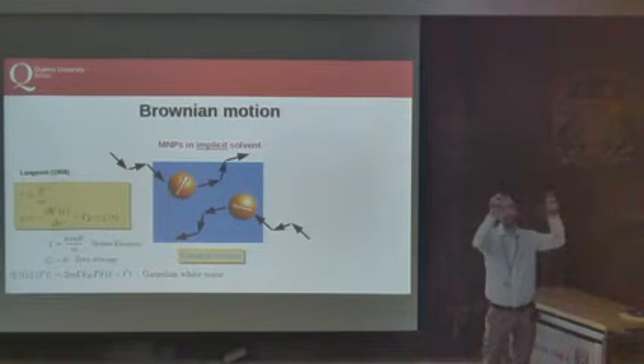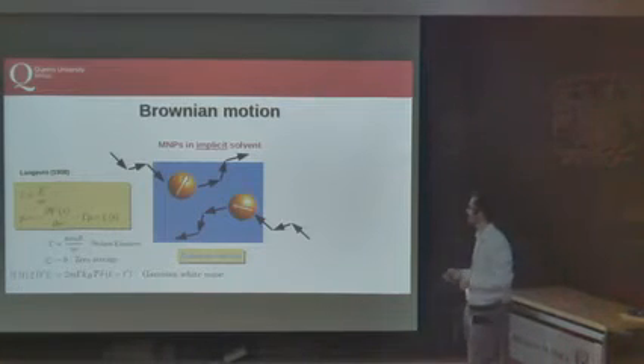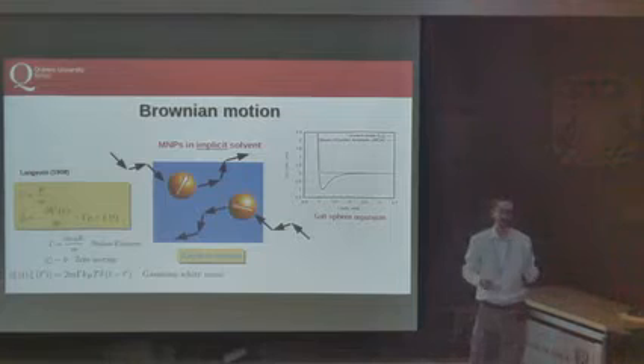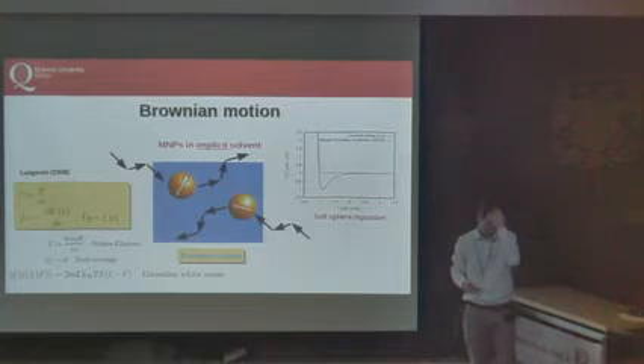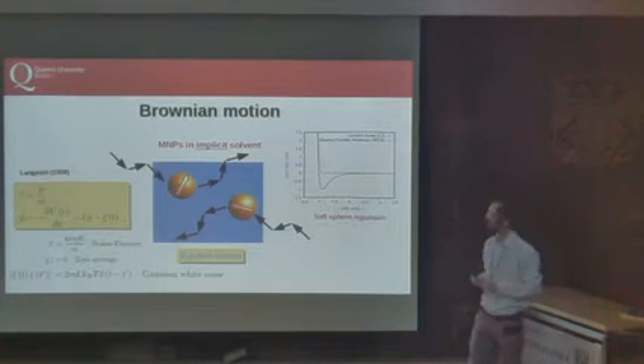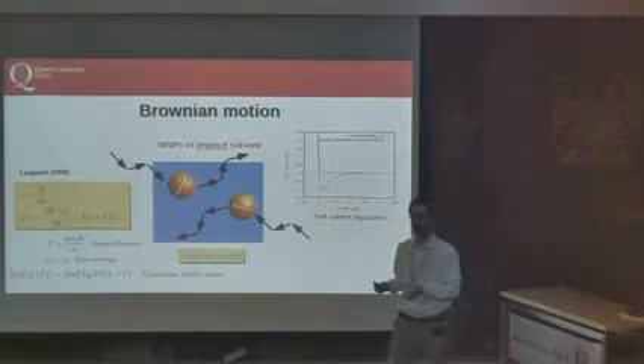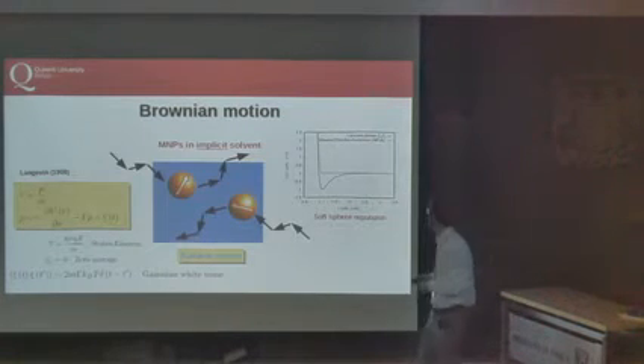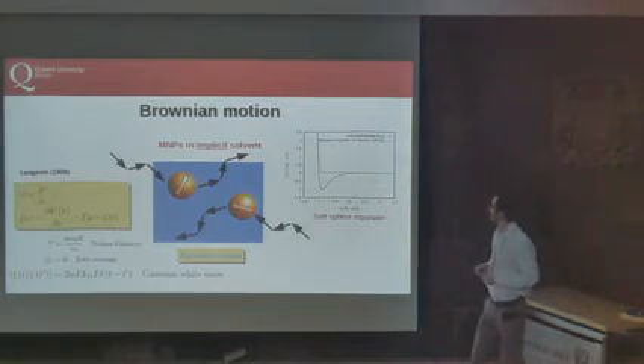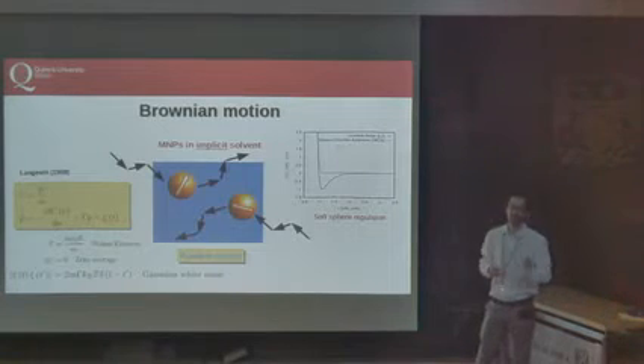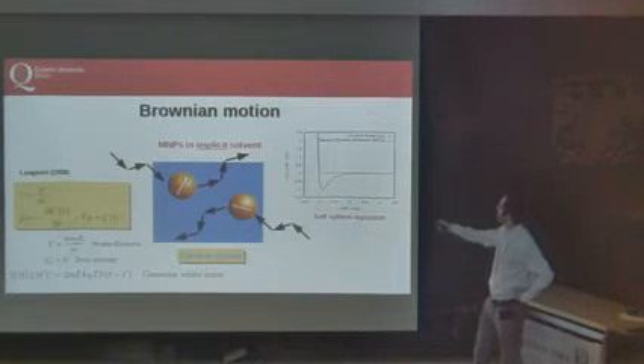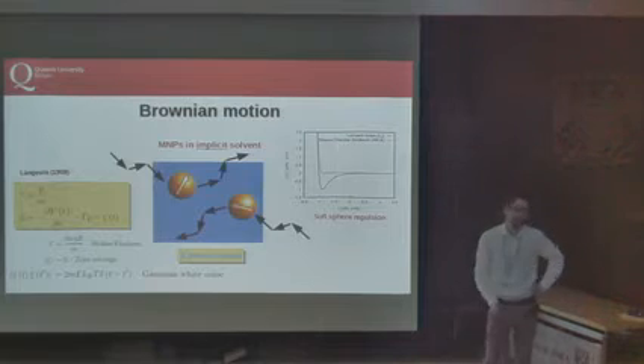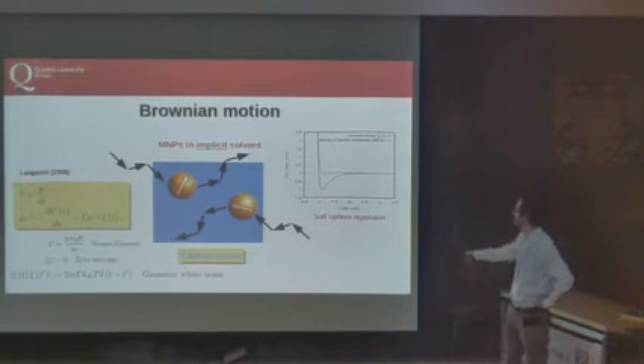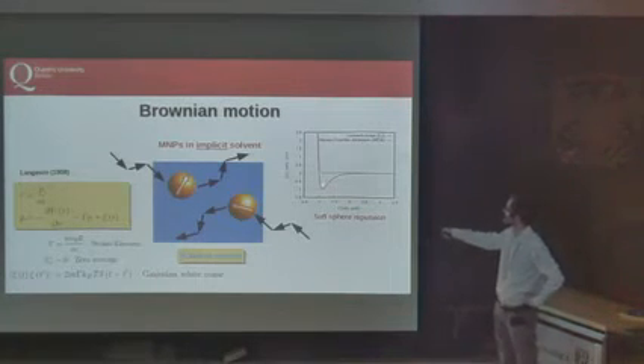So in this way, we can treat the random motion of the magnetic nanoparticles. We still have to provide a potential, since we want to focus on the effect of dipole-dipole interaction. We selected one of the most used of the simplest potentials, which is the Weeks-Chandler-Andersen potential. It is just a Lennard-Jones potential, which is truncated at the minimum.